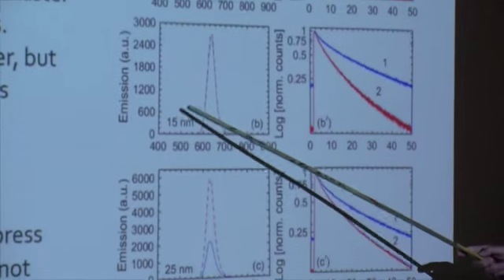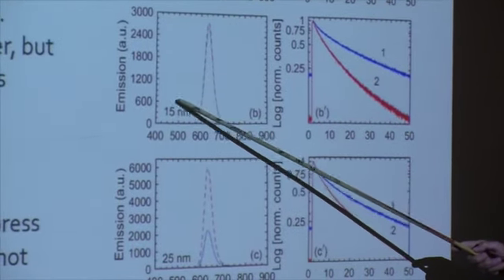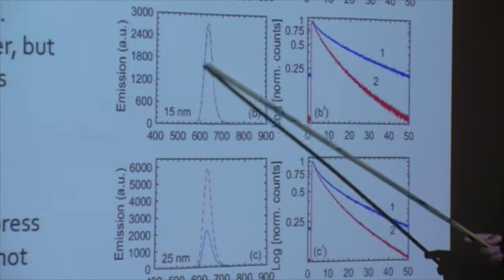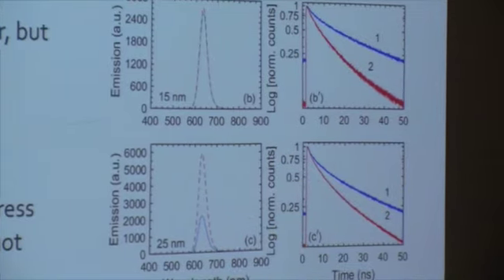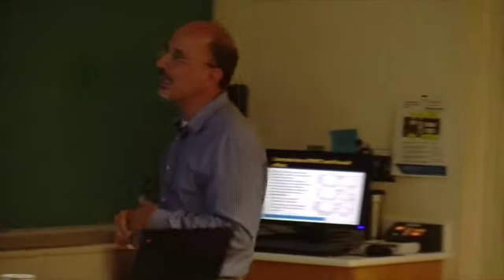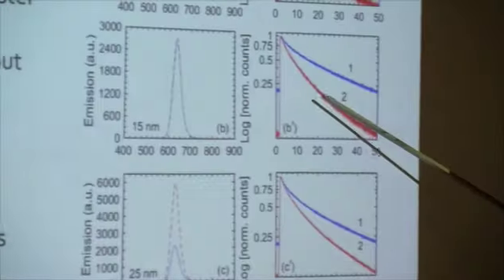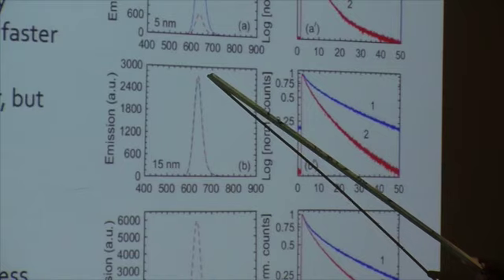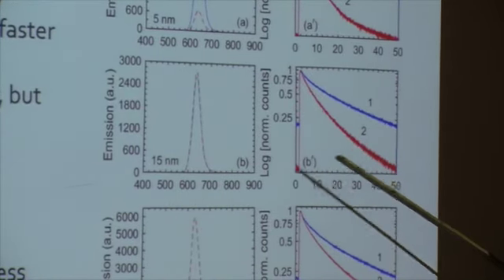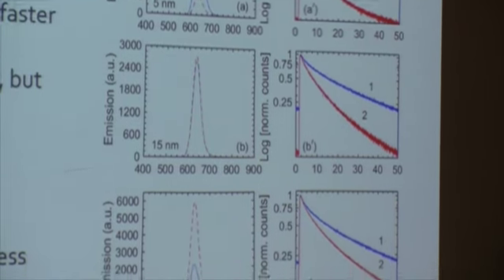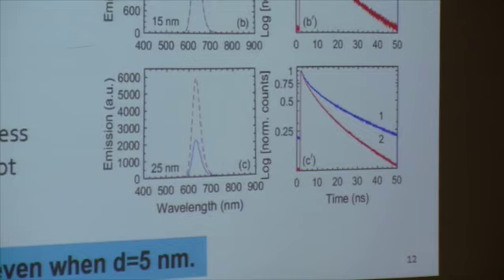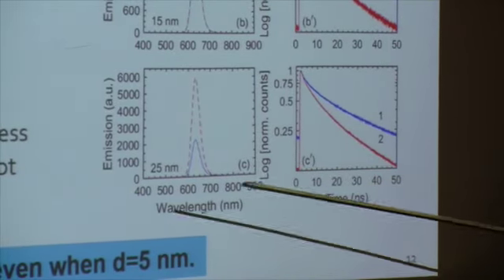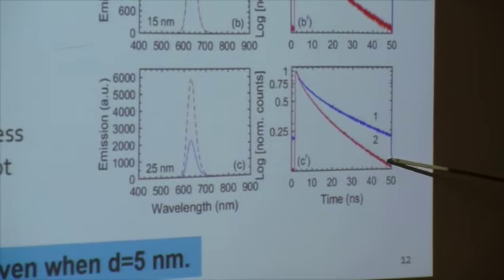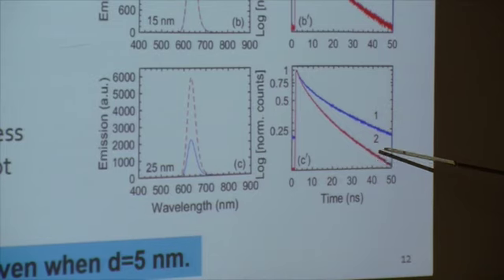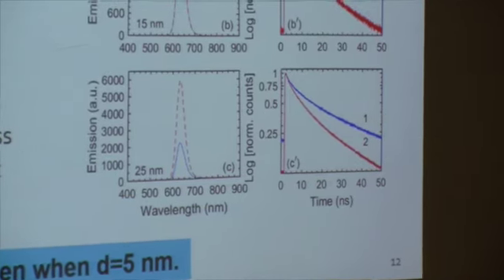Now, if you increase the thickness of the silicon oxide to 15, the emission becomes fairly equal. The emission on the glass and the emission on the glass and gold become fairly the same. But then again, you see that the lifetime on the glass and gold decays faster. But the emissions are similar. But then if you increase it to 25, you can see the emission of the quantum dot on the gold increases compared to without the gold. But still, the decay is faster. The emission of the quantum dot on the gold and glass is faster than on the glass. So this is happening.